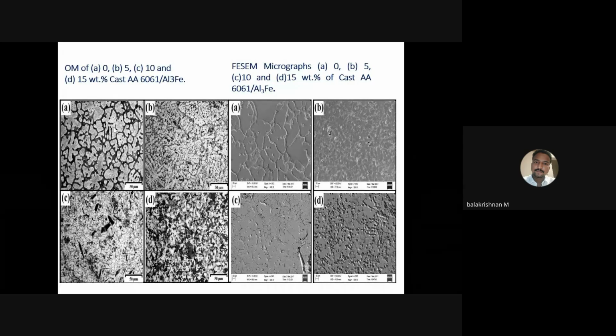It is a major alloying element of the matrix, that's why it occupied that space. The phase formation is due to the combination of magnesium and silicon, the major alloying elements, so it will dissolve at room temperature. The dendritic structure will be more compared to figure B.